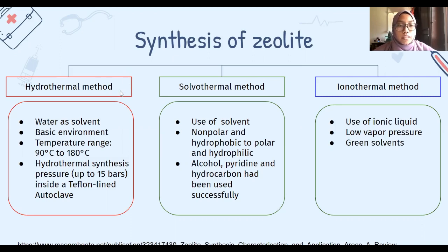The second method is the hydrothermal method, where the word hydro means water, so we use water as solvent, and it also needs basic environments. The temperature ranges from 90 to 180 degrees Celsius, with the hydrothermal synthesis pressure inside a Teflon-lined autoclave.